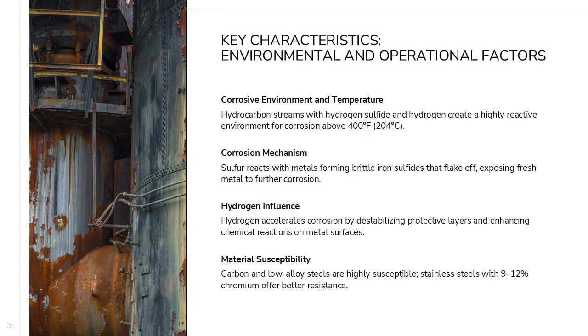The environment where high-temperature H₂S/H₂ corrosion occurs is typically hydrocarbon streams in refining and petrochemical units, including hydrodesulfurization and hydrocracking processes. These streams contain hydrogen sulfide and hydrogen, creating a highly reactive environment. The corrosion process starts above 400 degrees Fahrenheit, 204 degrees Celsius, and becomes more aggressive as temperatures increase. Mechanistically, sulfur reacts with metal surfaces to form iron sulfides such as FeS and Fe3S4. These sulfide scales initially provide some protection but are brittle and tend to flake off under thermal and mechanical stresses, exposing fresh metal to further attack.